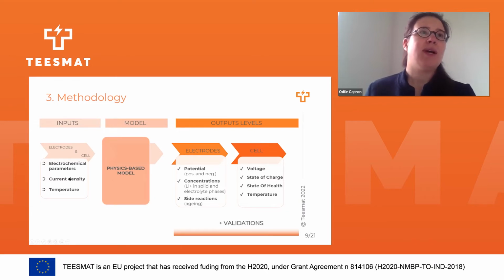What is also required as input for this kind of physics-based model is the current density. It's an input for the model, and it translates the condition under which the battery is working from the current profile point of view. The current density is mentioned because it's at the electrode level. The temperature is also an input. That's also to be considered because we will see later on that most of these electrochemical parameters are highly dependent on the temperature. So they are not constant during operation if the temperature is varying.